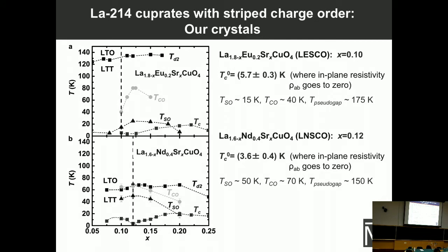So this one, LNSCO, is at 1/8. This is where the Tc has a minimum value. It's less than 4 Kelvin. And the other one is at slightly lower doping, LESCO. So in this material, stripe correlations are weaker. The Tc is lower than the onsets of spin and charge stripes, and all of these temperatures are much lower than the pseudogap temperatures for these two materials.